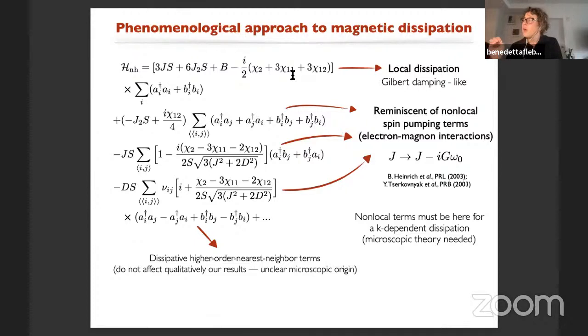Now, it was found that the acoustic mode has a broadening, a relaxation time, that is k-dependent, which signifies that there is a non-local dissipation acting in the system. So these are the terms that we find. And for some of you that are maybe familiar with the phenomenology of spin pumping, these terms are really reminiscent of non-local spin pumping terms, that are due to electron-magnon interaction in this case.